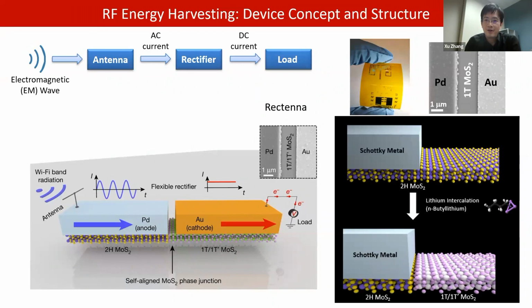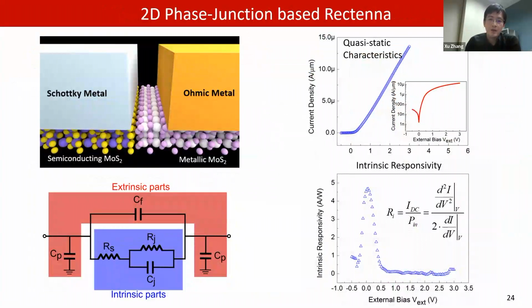We developed a self-aligned lateral semiconducting-metallic phase junction of MoS₂ and built a Schottky diode in which the boundary of the Schottky junction perfectly aligned with the boundary of the MoS₂ phase junction. This structure allows a simultaneous reduction in series resistance and parasitic capacitance. Here shows how we model the circuit and the DC characterization of the MoS₂ phase junction diode. It shows a high intrinsic responsivity of 4.7 ampere per watt at 0 external bias.